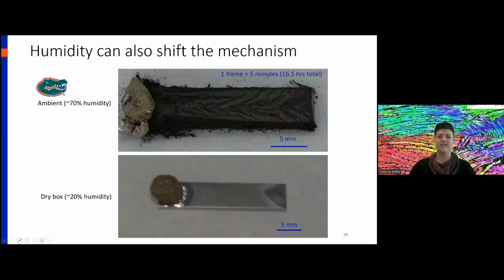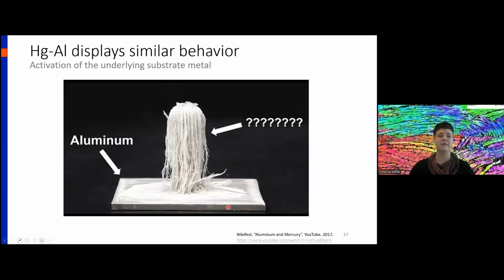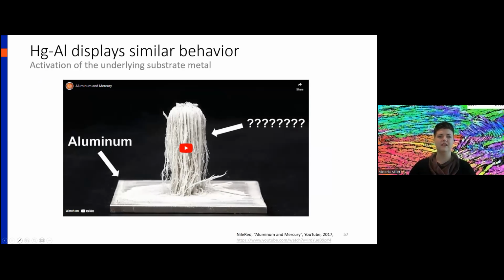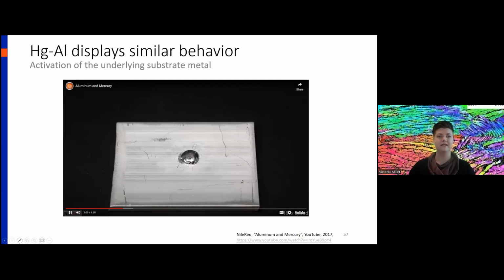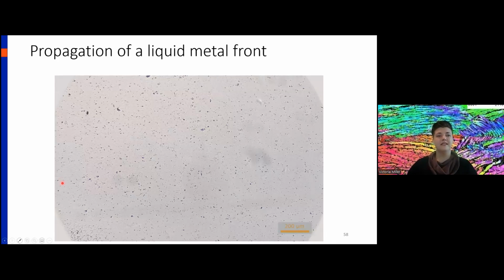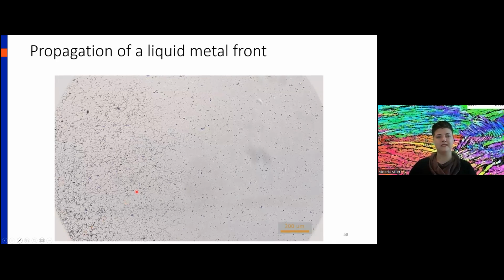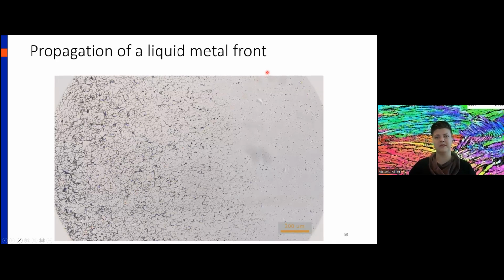I'll note that mercury on aluminum displays very similar behavior. This is the fairly famous Nile Red YouTube video where you get growth of this aluminum oxide tower when the aluminum is activated by mercury. And it may or may not play real quick, but if it doesn't, that's fine. In real time, this process is really slow. So I set things up for a time lapse. So you can see propagation of this liquid metal front going across the aluminum specimen.